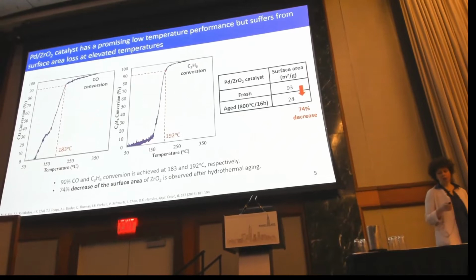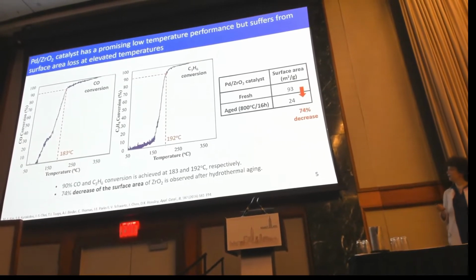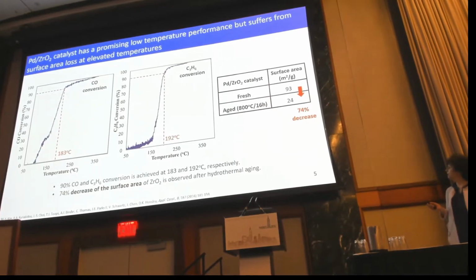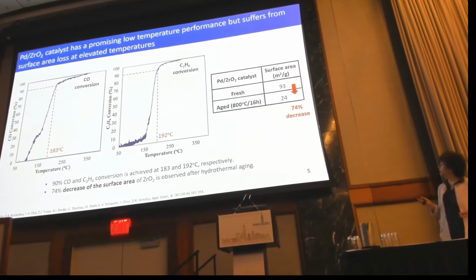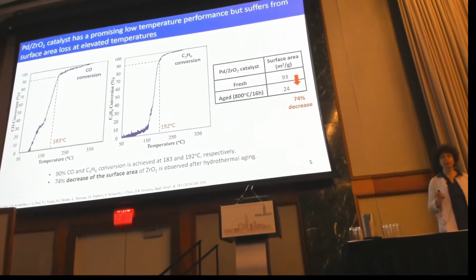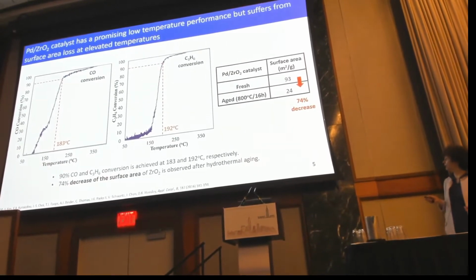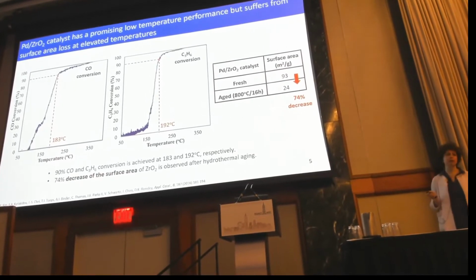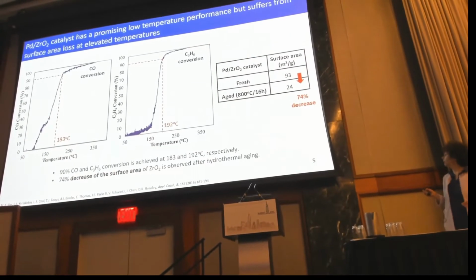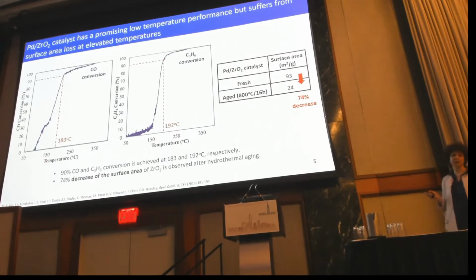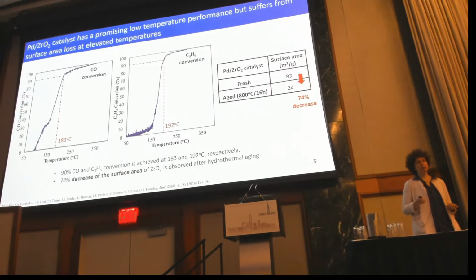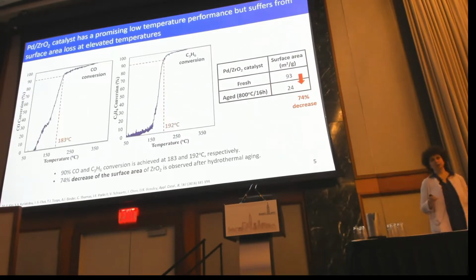One of the weaknesses of this material is that its surface area drops significantly after hydrothermal aging. So what we see here is that fresh palladium on zirconia has a surface area of 93 meters squared per gram, and when this material is hydrothermally aged at 800 degrees C for 16 hours, there is a 74% decrease in the surface area, down to 24 meters squared per gram. So at this point we're wondering, is there a way for us to increase the surface area of zirconia?